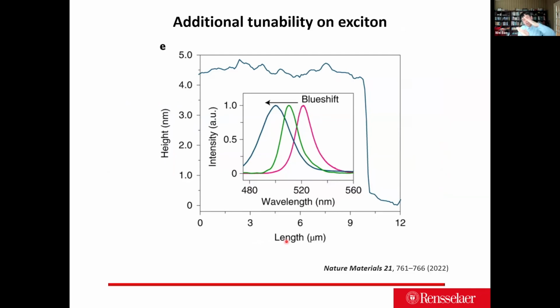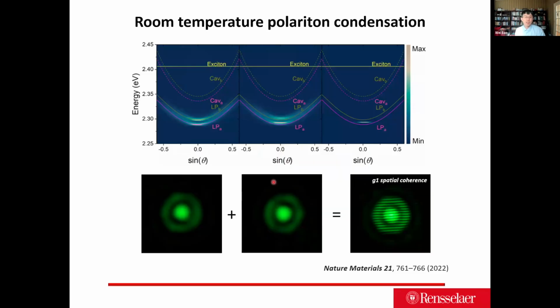If you make the nano cavity really small, you can even see a blue shift. In one of the draws, we made the gap as small as 4 nanometers, and we can see this blue shift. It also shifts the cesium lead bromide sample into a quantum well, at around 400 nanometer wavelengths. Those are really interesting experiments. With this sample, we can see really nice polariton condensation.